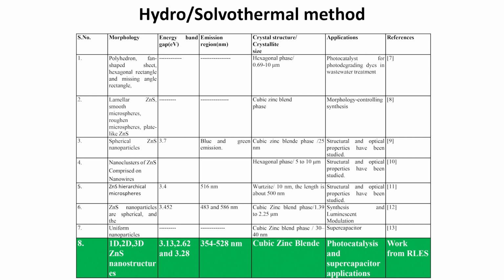We have developed in our lab 1D, 2D, 3D ZnS nanostructures, and the energy band gaps are 3.13, 2.62 and 3.28 electron volt. The emission region is lying between 354 to 528 nanometers, and the crystal structure obtained is cubic zinc blende, and the potential applications are photocatalysis and supercapacitor applications.